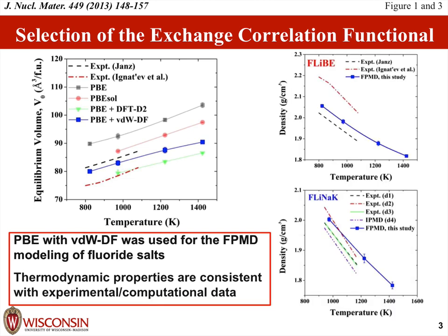With the selected exchange correlation functional, thermodynamic properties of fluoride salts, such as the density, bulk modulus, and coefficient of thermal expansion, were predicted and are consistent with the experimental measurements.